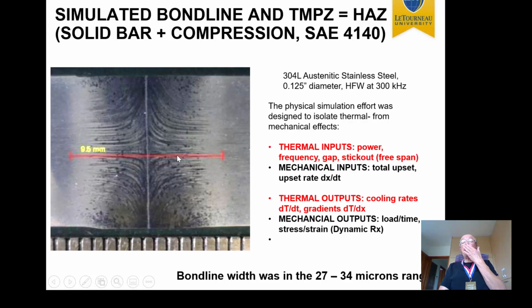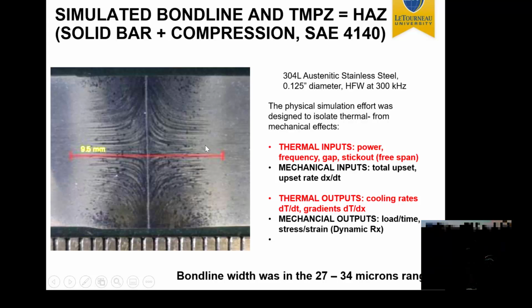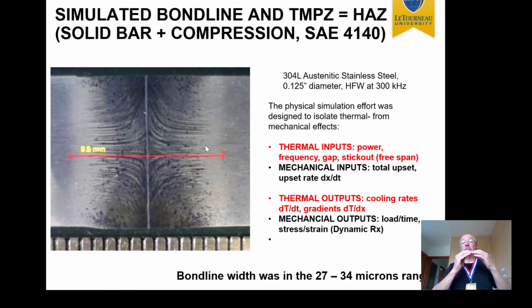And here you can see that we looked at the thermal inputs, which were the power, frequency, and the gap between the material, and then mechanically the upset rate, and the outputs were cooling rates, temperature gradients, and total loading time. Important to notice again that this bond line doesn't seem to change no matter what we did with the thermomechanically processed zone. So again and again the same topic comes up. The bond line does not change much, 27, 34 microns.